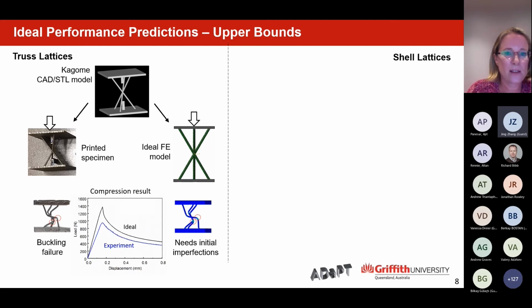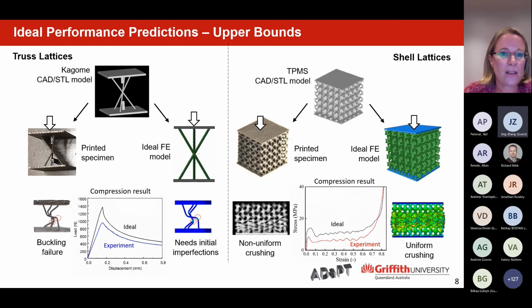For the shell lattices, we see quite similar things. Again, there's a TPMS model here, so a triply periodic minimal surface design, where we produce the ideal FE model. And again, we see a higher stiffness, a higher plateau stress. Yes, we're capturing the failure mechanisms properly, but everything is very uniform and symmetric, while in the experimental result, we do see non-uniform behavior because of imperfections. Now, I think that is the assumption, right? That these differences are due to the imperfections in the structure.